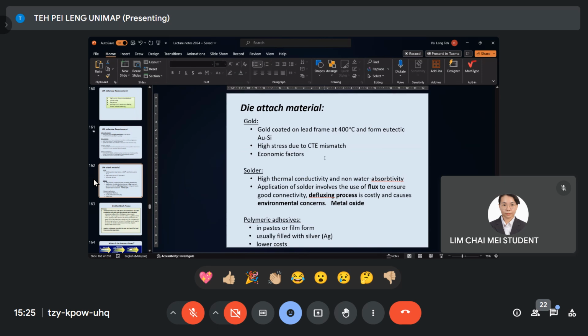The 400 degrees Celsius will cause CTE mismatch, then you will generate high stress to the entire package. And also it's expensive, so you will have an economic factor. But one thing that is good is the gold CTE is much lower compared to polymer. That is the only good thing. So you can minimize the CTE mismatch. But then this one and this one will cause high stress.